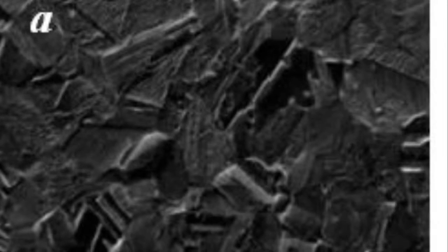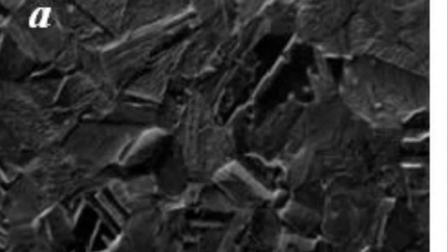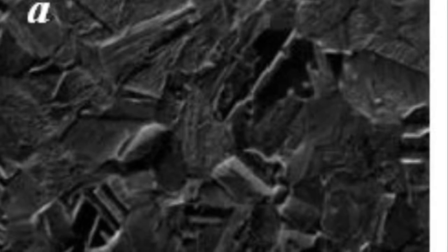The patterns in image B, which represents a portion of the grain boundaries in the wire, show an increase in length in the longitudinal direction, and image A shows the reduction in width in the transverse direction. The shape of the grains became increasingly long and thin. This texture is frequently observed in wire drawing and is known as fiber texture or fibrous texture because it resembles the arrangement of fibrous material.